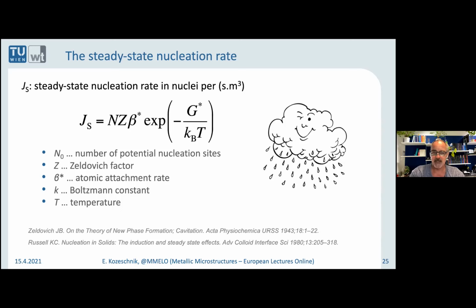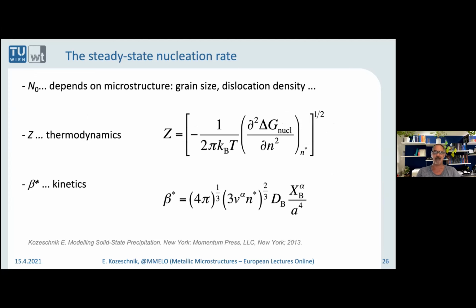And that will already indicate that G star is a very important quantity, because the exponent of G star is a term that changes by orders of magnitude if you change G star just by a little bit. I will show examples later. And the three pre-exponential factors, N, Z, and beta star, are more or less related to the thermodynamics, the kinetics, and the microstructure.